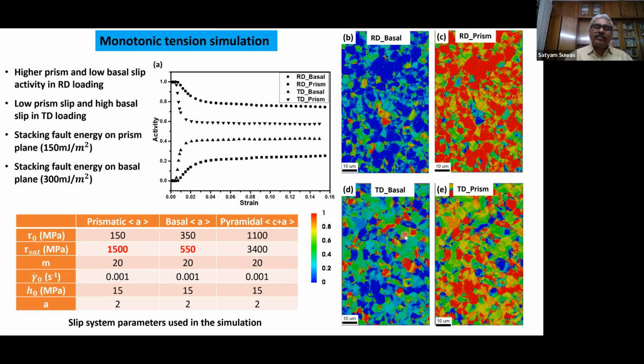And then similarly for the TD case, the trend was different. For basal, it has shown more hot spots here and there, in all these cases. And then TD prism slip has shown again lots of hot spots here, higher propensity of Schmid factors here.